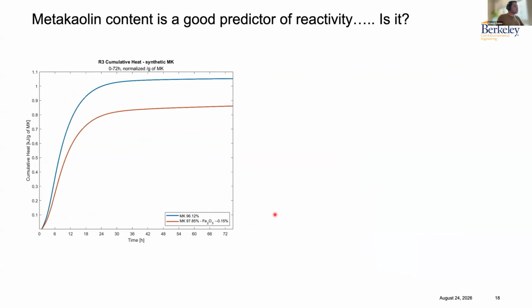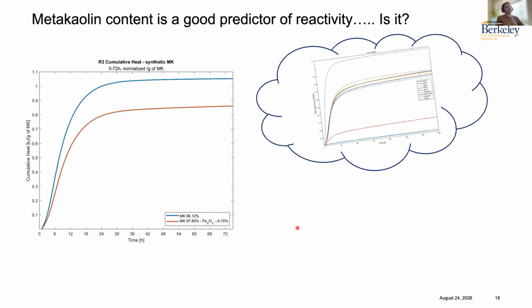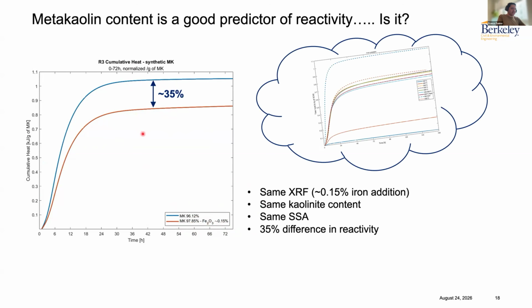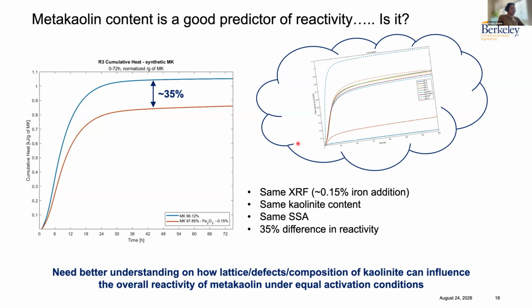This is the work of one of my students right now. He's producing synthetic clays in the lab by hydrothermal aging. And one of the things that we could do was to introduce doping of minor additions of iron in these clays. And he was actually able to reproduce this 35% difference by including, look at the number, please, 0.15% iron in one of the starting materials. So again, these two materials have the same XRF. They differ essentially in 0.15% iron addition in one or the other, the same kaolinite content, the same specific surface area, and still have 35% difference in reactivity. So we need better understanding on how lattice defects and composition of kaolinite can influence the overall reactivity of metakaolin under equal activation conditions.